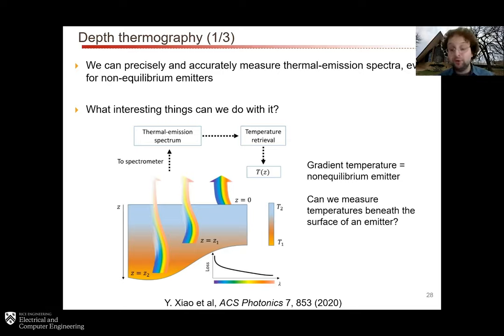One of them is that both of those materials, and actually any material with vibrational resonances, has emissivity that is dependent on temperature. Not too dependent, but it is dependent. And so you have to know what that temperature dependence is if you're going to have a large dynamic range of temperatures and want very precise measurements. Also, those samples have sharp features in the spectrum as a result of vibrational resonances, optical phonons and things like that. That's very useful to make sure that your measurement is working, but it's also potentially troublesome, because if you divide by something that has a sharp feature, you can get that feature in your normalized measurement if you're not very careful.